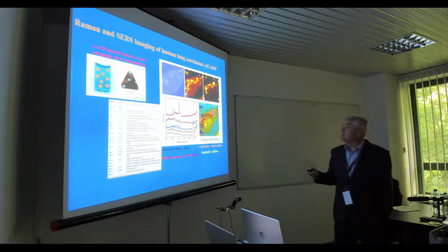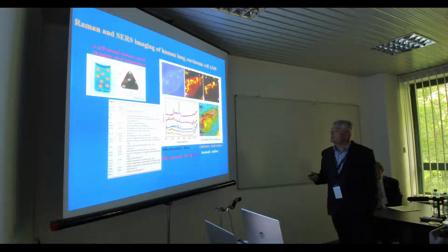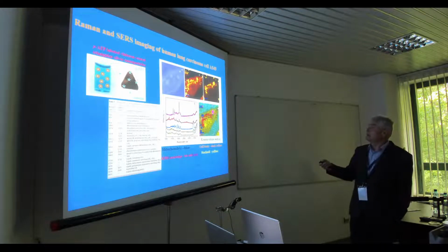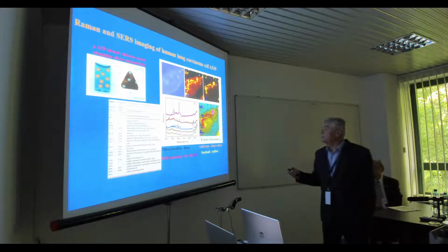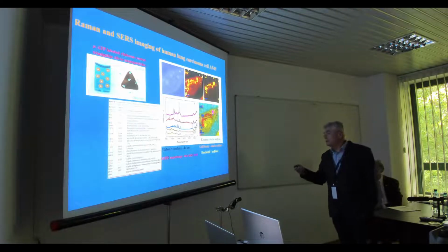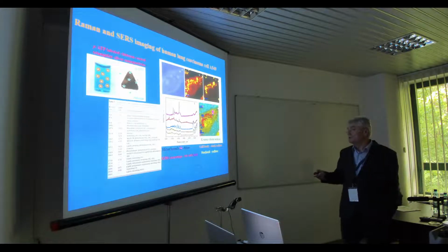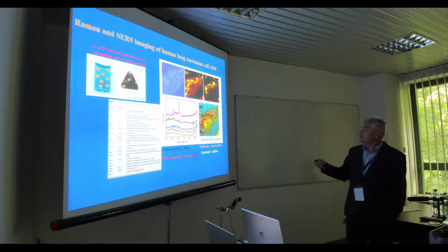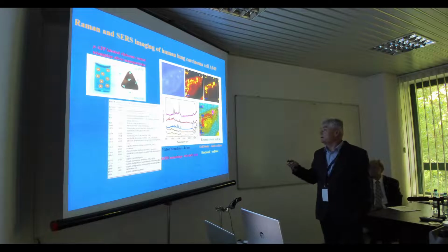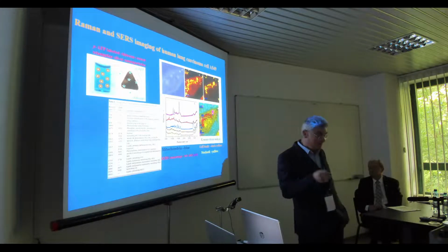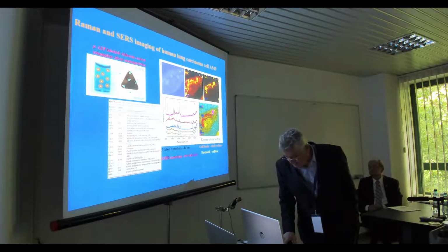We can identify by specific band not only the presence of nanoparticle, which is marked in red, inside the cytosol, but also you can detect the cellular components, nucleus, mitochondria in blue, and it can map the entire cell, and specifically find the nanoparticle. This is with no heating, and you can repeat this kind of experiment.